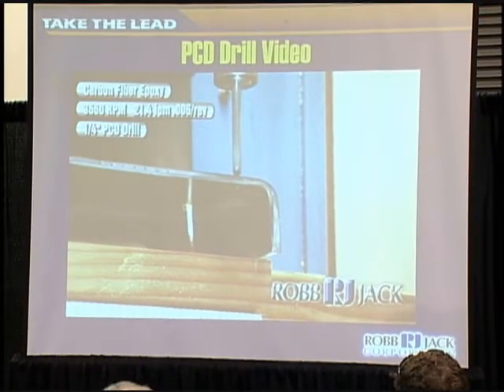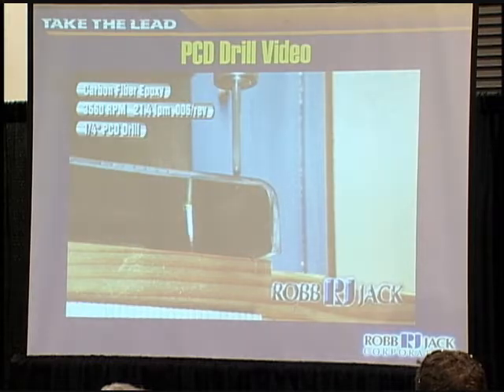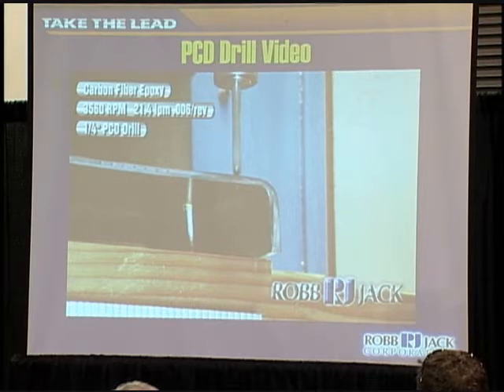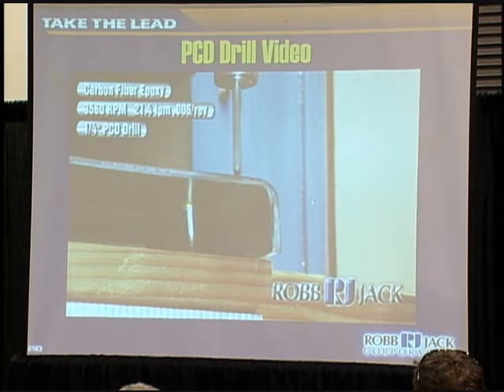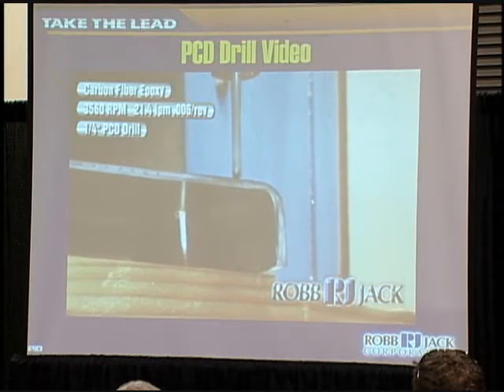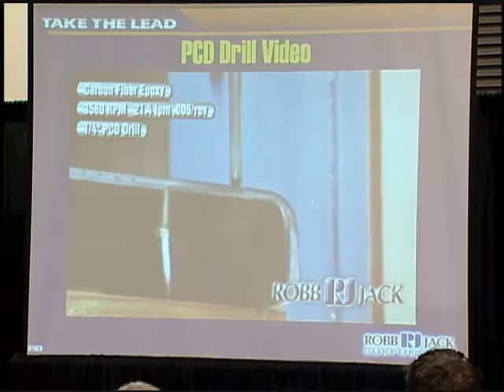So here we're going to show a video of the drill that we're passing around, and that's actually the part that was cut. The thing to note is a lot of times speeds and feeds are done incorrectly, and that's what gives you a lot of poor tool life. When we cut this part, you'll see actual fibers and chips being formed. There's a lot of powder being formed, but you'll actually see chips being formed. That's because the feed rate is fast enough to actually form chips. We're running this 1/4-inch tool at 3,560 RPM and 21.4 inches per minute.